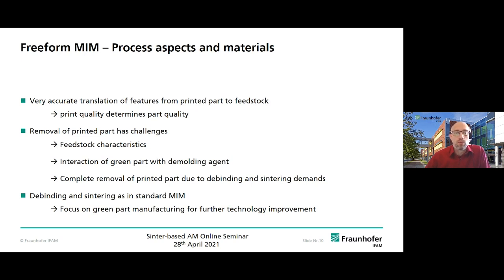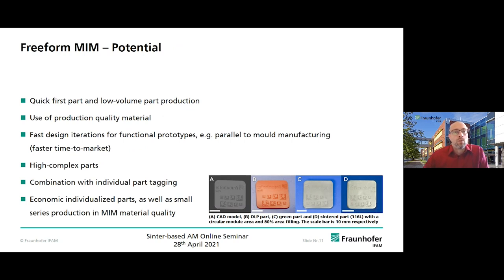For the debinding and sintering, I would say that it's mainly the same as for MIM, so this has not been a great issue, and we can focus on these other points. We see some potential, especially for low volume part production, and when you come from the MIM side, you can make use of your production material for prototypes and small series parts. You have a very fast time to market when you make design iterations, for example, parallel to a classic mold production when you look at the MIM process. But you may also make more complex parts than you can with MIM because you don't have to do the demolding by opening a tool and ejecting a part, so you are more free there in the complexity.